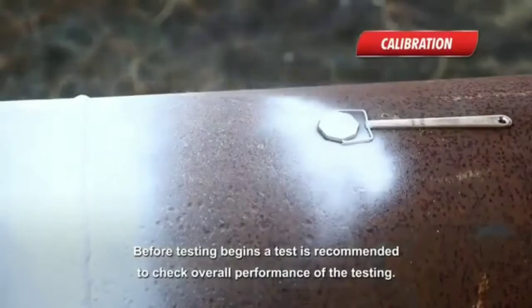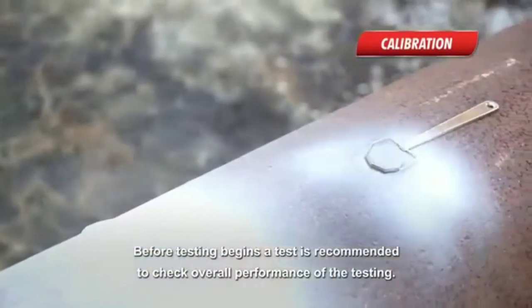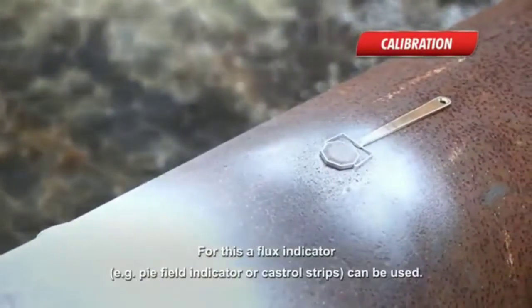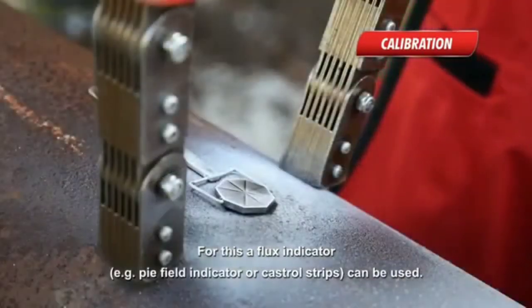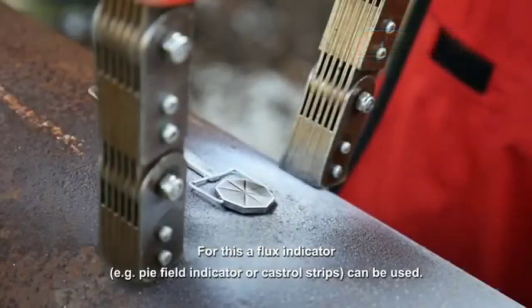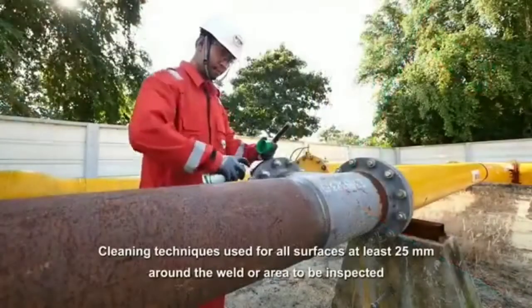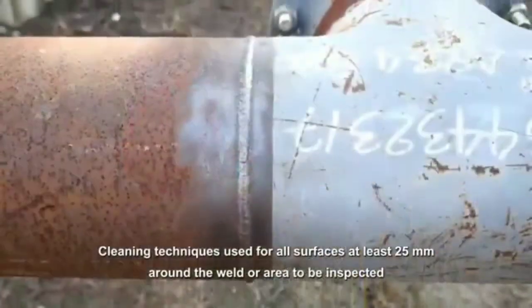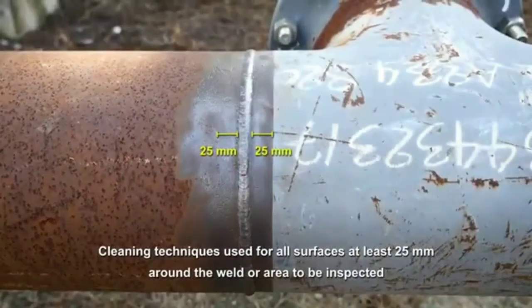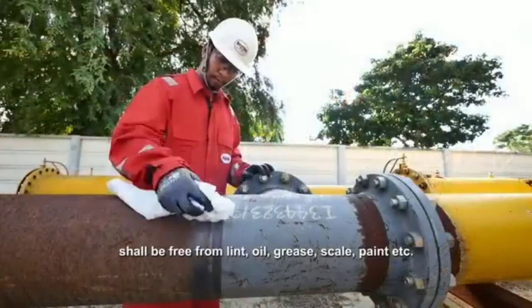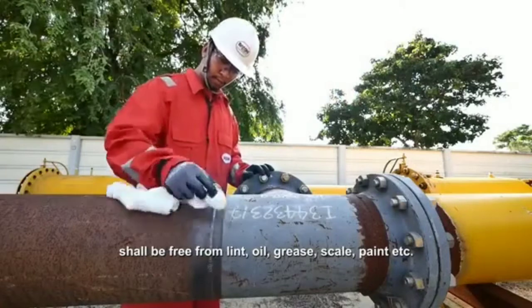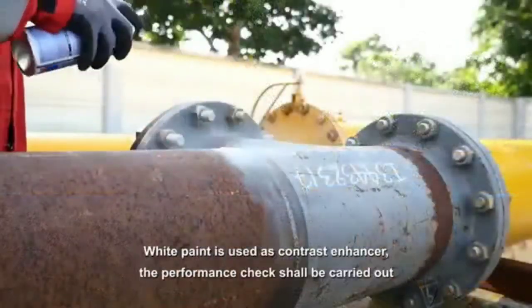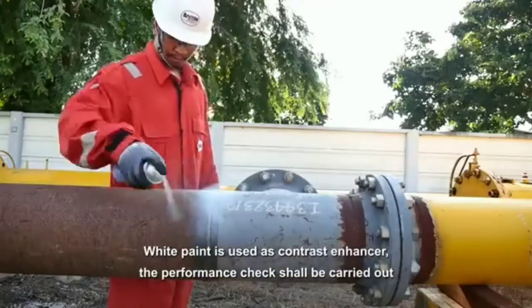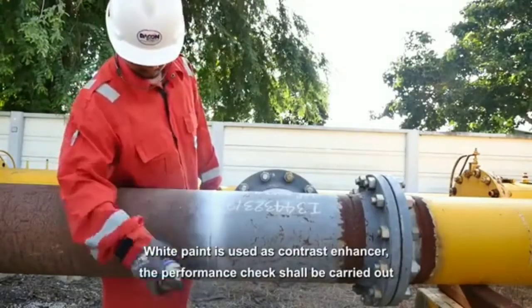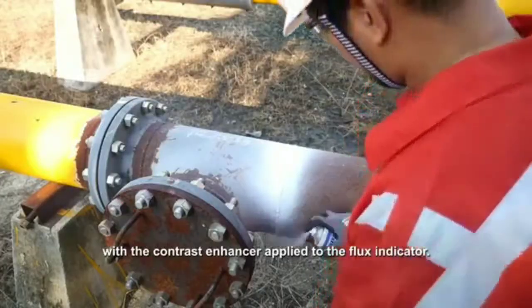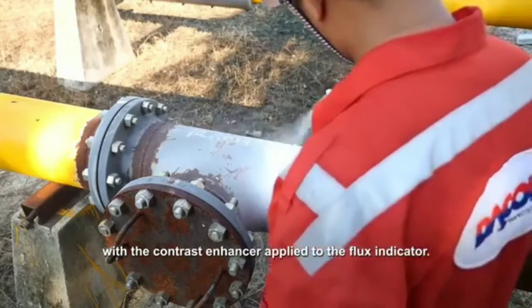Before testing begins, it is recommended to check the overall performance before the procedure. For this, a flux indicator can be used. Cleaning techniques are used for the surfaces at least 25 mm around the weld or area to be inspected, and it should be free from lint, oil, grease, scale, paint etc.. White paint is mostly used, and a contrast enhancer applied to the flux indicator.